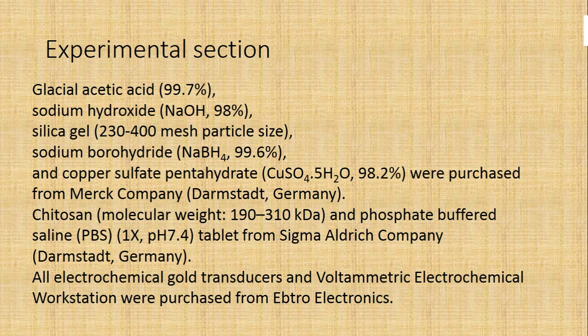We used the following chemicals and apparatus: glacial acetic acid, sodium hydroxide, silica gel 230-400 mesh, sodium borohydride, copper sulfate pentahydrate, chitosan 190 to 310 kilodaltons, phosphate buffered saline PBS, electrochemical gold transducers, and a Voltammetric Electrochemical Workstation by Ebtro Electronics.